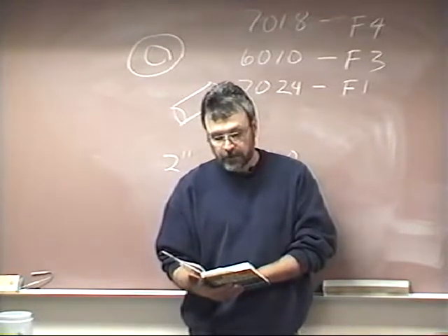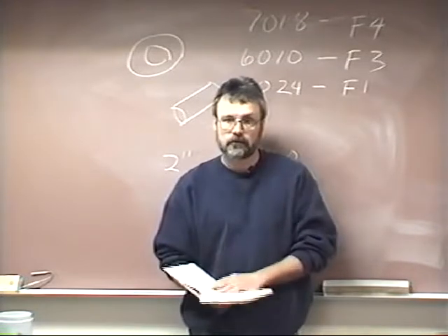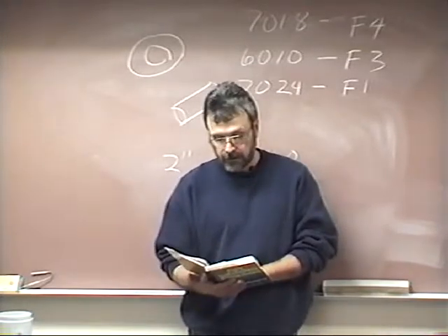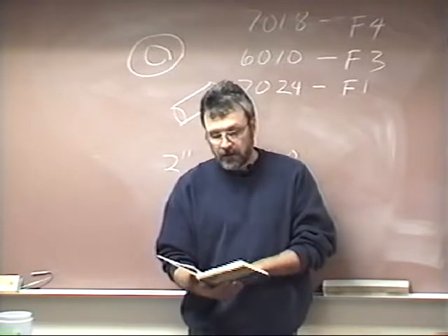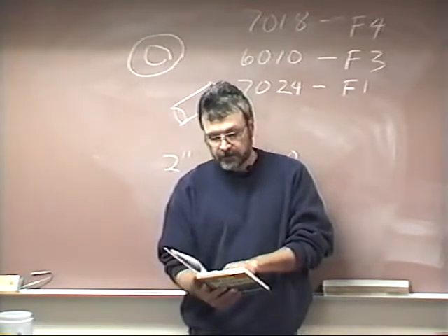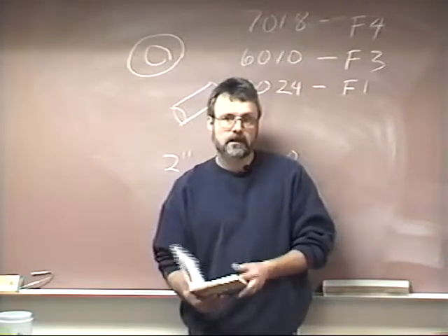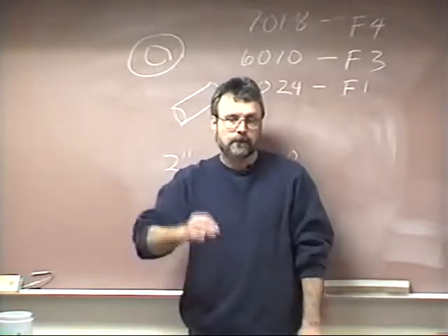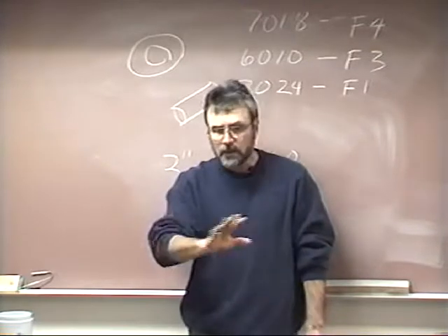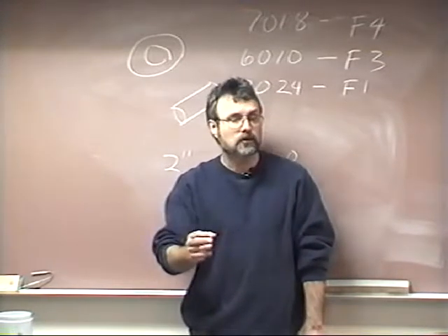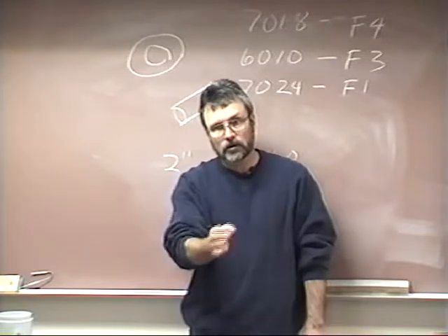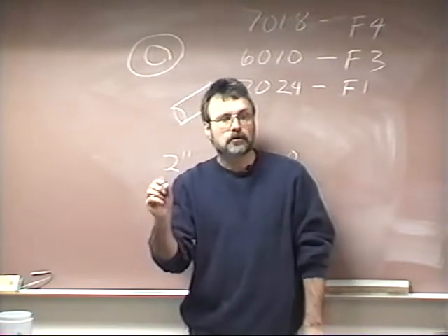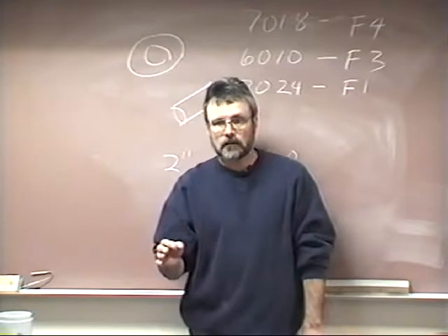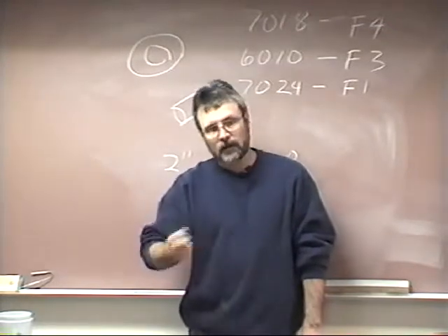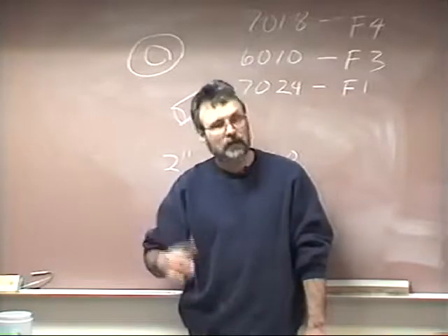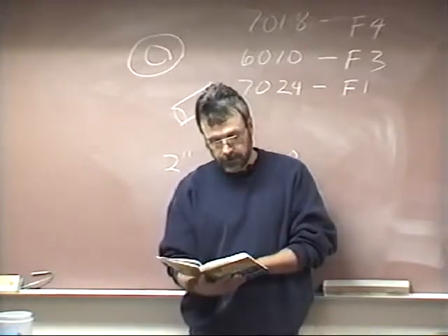Okay, having passed the visual inspection, 4 specimens are extracted from the welded pipe as shown on page 227, comprising 2 face bends and 2 root bends. Doesn't matter if we're doing plate or pipe, that's what we're going to take out for you guys. Those bends must be inspected for the following: slag inclusions, cracks, and incomplete fusion. When we put them in that bend test jig and we bend them, like I said, it's 1/8 of an inch. Any of these things can come up, but if it's less than 1/8 of an inch, it's okay. If it's on the edge, on the corner of your coupon, it can be up to 1/4 of an inch long as it's clean. But if it cracks and we put it under the microscope and I see slag in there, that's an all shot. You're done.